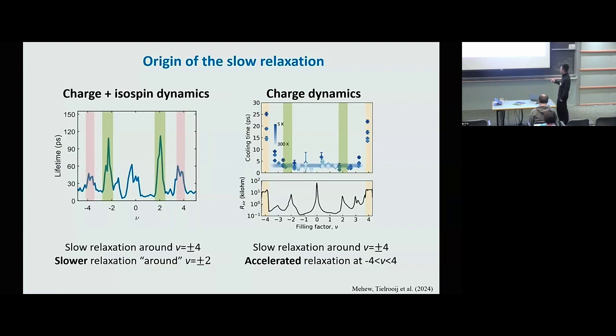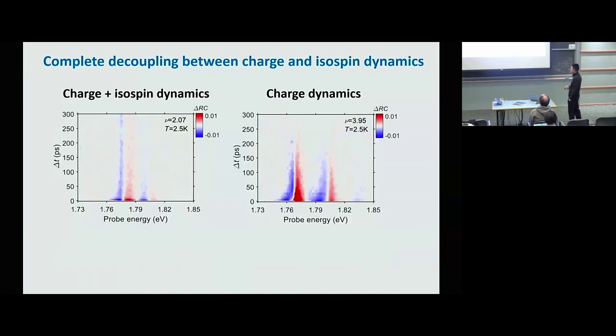But in our case, we actually see very slow, even slower relaxation at around plus minus 2. And that means that this direct comparison tells us that this cannot be coming from charge dynamics, and most likely it's from isospin dynamics. And another thing it tells us is that at this point, the charge and the isospin dynamics are completely isolated, decoupled.